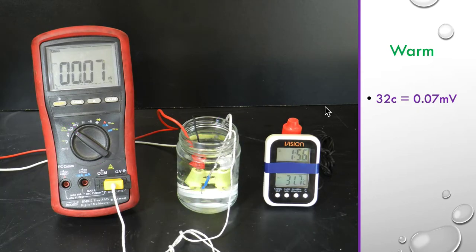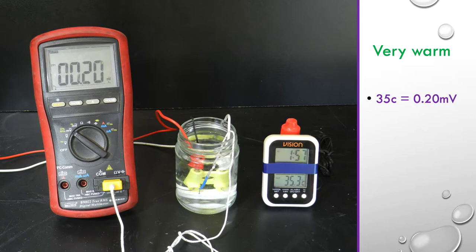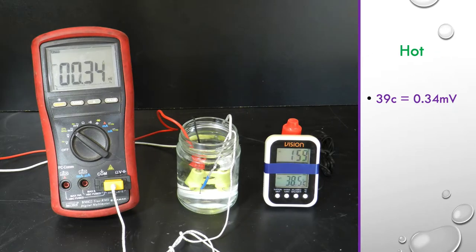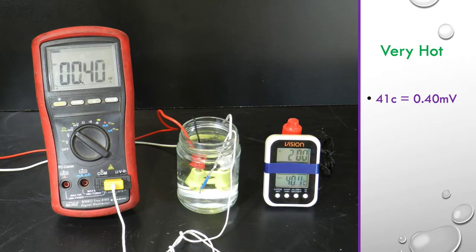So you can see here the temperature's now gone up to nearly 32 degrees and our reading has gone up to 0.07 of a millivolt. So the temperature's gone up and our thermocouple reading has also gone up. So we go to very warm, so we're now up to 35 degrees C, and we've come right up to 0.2 of a millivolt. And we get up to hot at 39 degrees C, and we're up to, as you can see there, 0.34 millivolts. And then very hot at pretty close to 41 degrees, we've now got 0.4 of a millivolt or 400 microvolts.